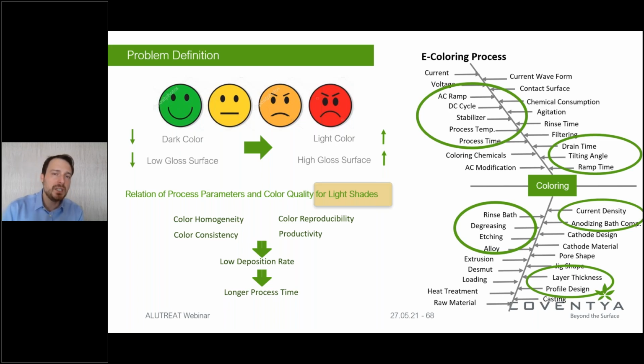So here we see a much broader effect of the AC ramp, DC cycle, stabilizer amount, process temperature, process time, even the rinse bath. If you leave your profiles too long in the rinse bath, the color will be fading out. This is one of the biggest problems that you're ever going to face with light champagne colors. Therefore, for lighter shades, it is not enough to get these pre-treatment and anodic oxide cycle completely perfectly in line, but you need to do and control the coloring.